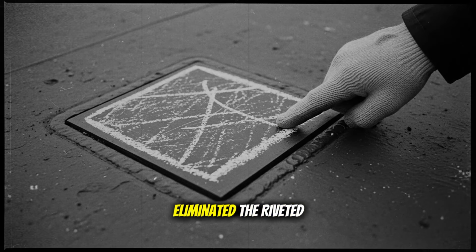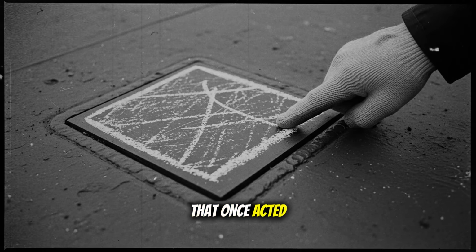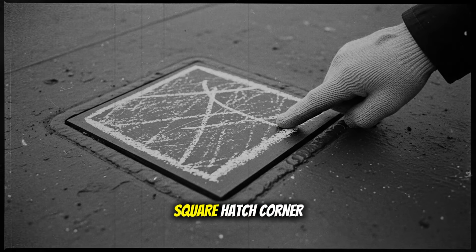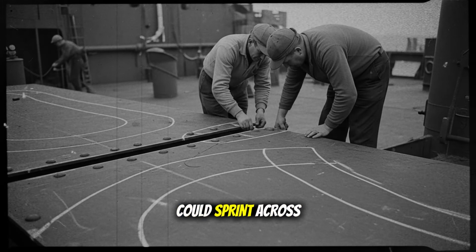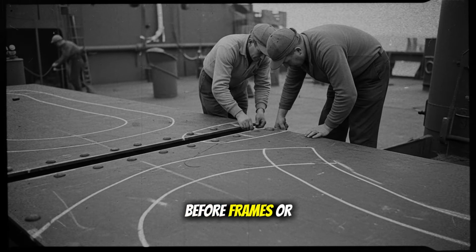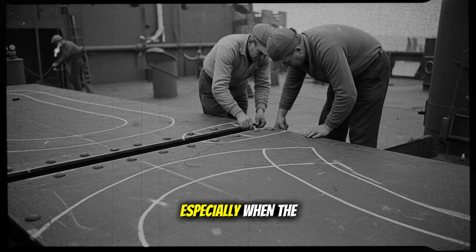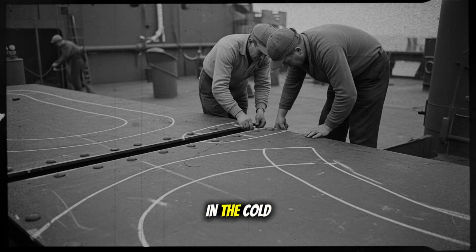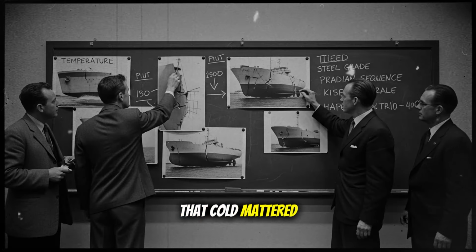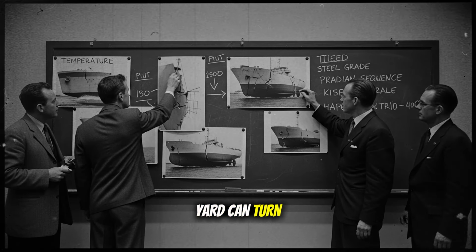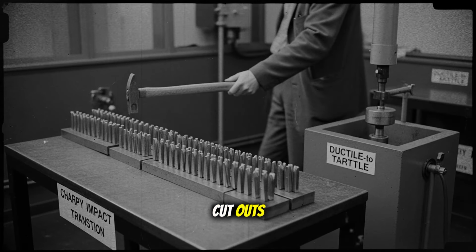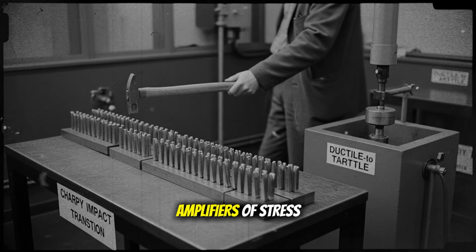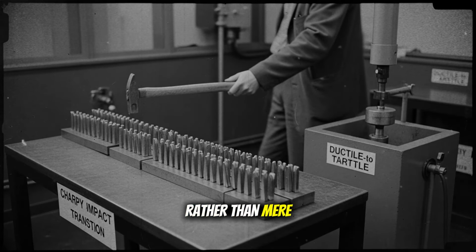Welded construction eliminated the riveted discontinuities that once acted as brakes, so a fissure born at a square hatch corner under residual tension could sprint across a deck and down a side shell before frames or bulkheads could arrest it, especially when the steel's ductility had collapsed in the cold. That cold mattered more than pride would admit, because steel that bends and forgives in a temperate yard can turn glass hard at sea, crossing an invisible threshold where toughness drops in tiny notches. Tool marks, square cutouts, abrupt geometry become amplifiers of stress rather than mere imperfections.